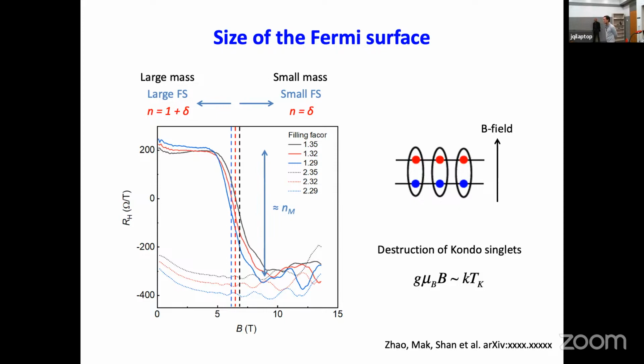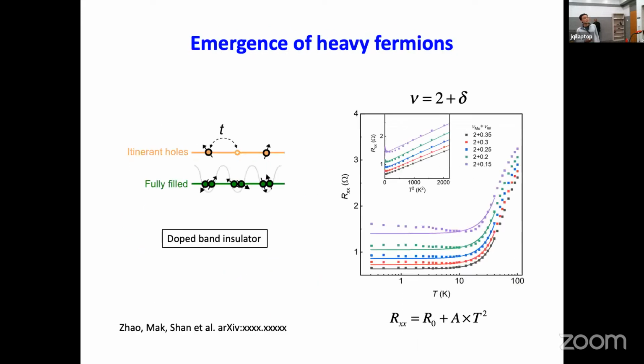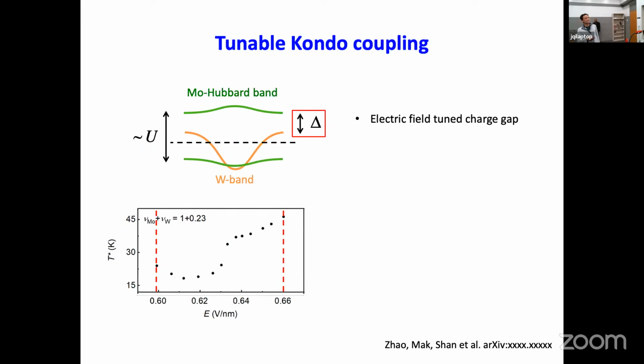Yeah. Do you see a change of Kondo temperature as a function of the vertical displacement? Yes, it's actually this data here. Oh, I'm going the wrong direction, sorry. So this is tuning the electric field at a particular doping. The electric field changes the relative displacement of the Hubbard bands and the tungsten band, right? So these two dashed lines basically correspond to the edge of the tungsten band touching the upper Hubbard band or touching the lower Hubbard band.